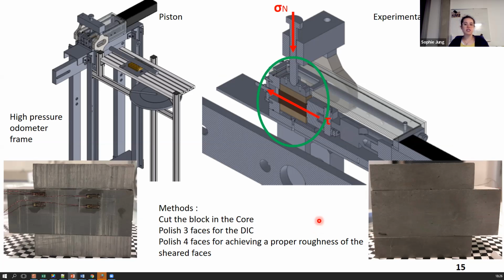Moreover, in order to use digital image correlation, the lateral faces of each of the blocks, so you can see it here, are polished to bring out the microstructure of the rock and thus create a natural speckle. You can see here that the blocks are not polished, so it's quite a different aspect. Also, the 4 surfaces sheared during the experiment are polished so that the roughness of the faces is as similar as possible to the roughness of the sheared fracture present around the underground laboratory structure.